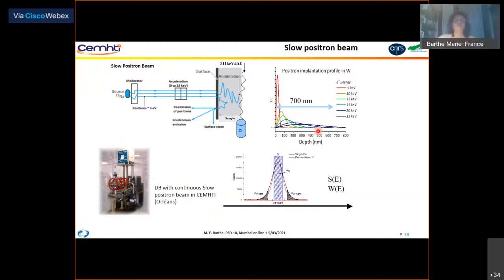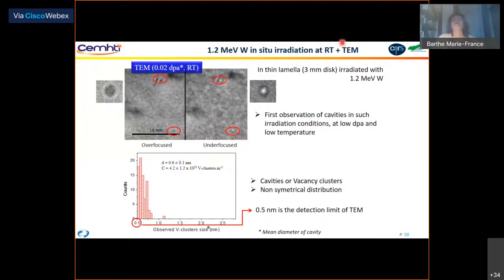and we measure the low momentum annihilation fraction S and the high momentum annihilation fraction W as a function of the energy of the slow positrons. So if we look first at the results at low dpa and low temperature, irradiation has been performed at room temperature and with 0.02 dpa.